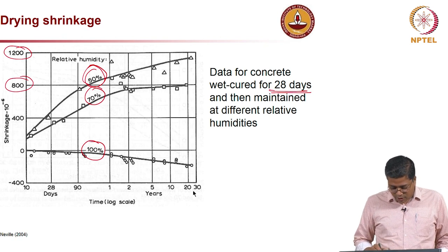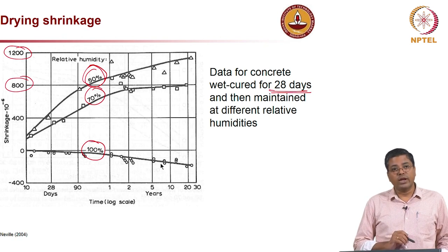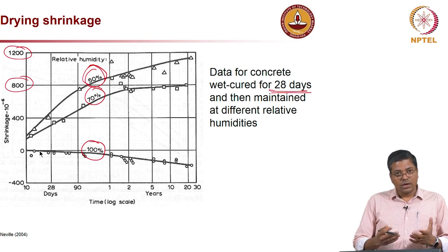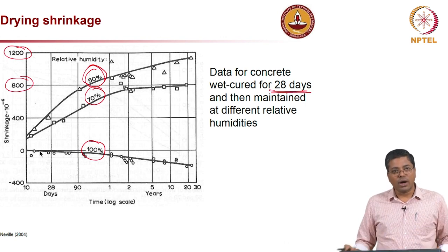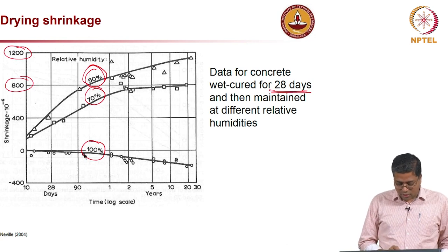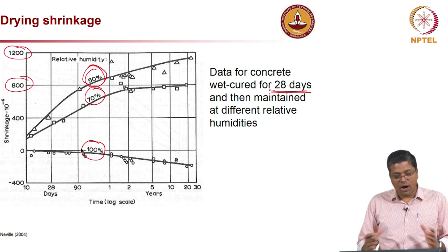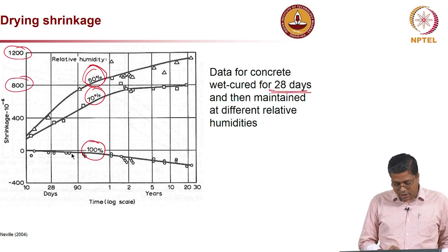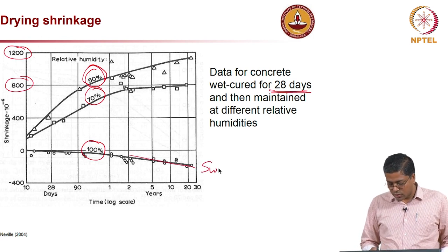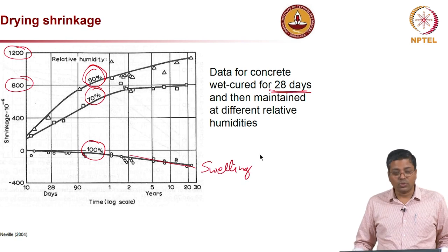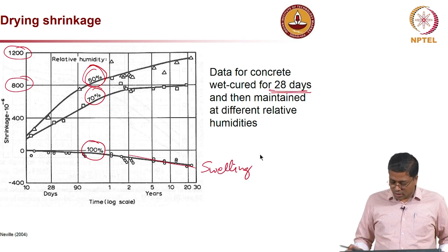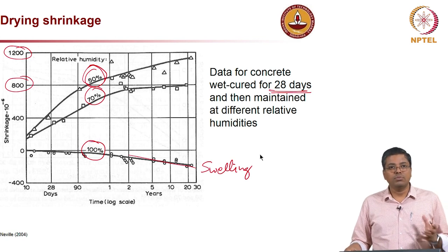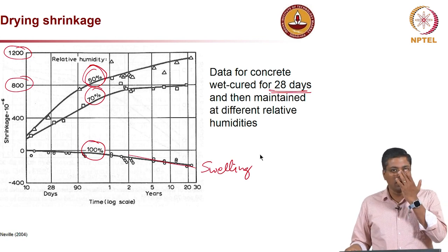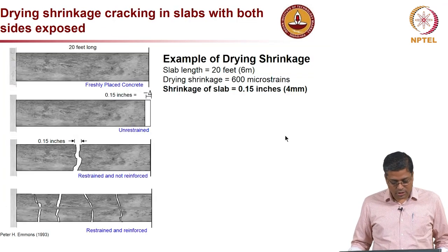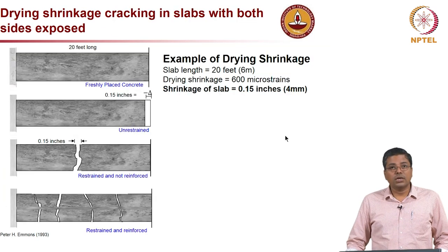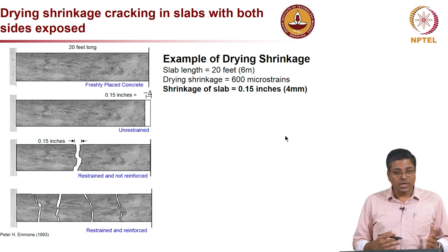And then when you look at the 100% humid environment, the moisture from the air was absorbed by the concrete, and it actually leads to swelling. This is a case of swelling, okay. So it is very clear that the ambient moisture condition, or the humidity condition, really plays a role in drying shrinkage. Now drying shrinkage cracking in slabs with both sides exposed.